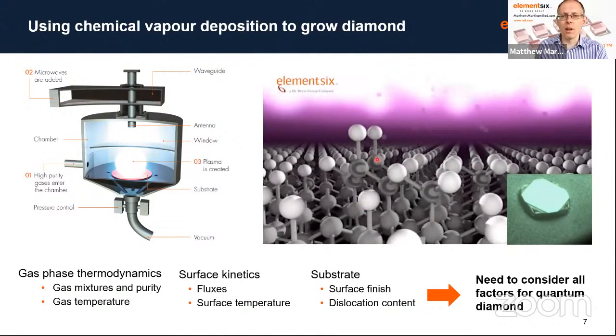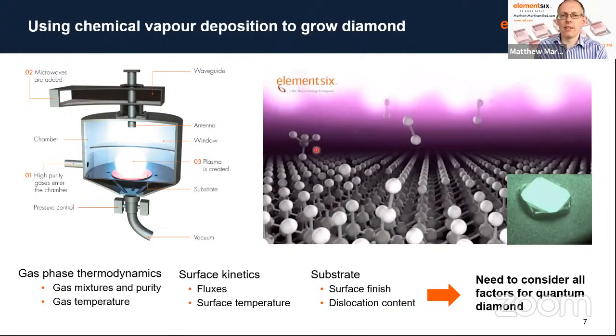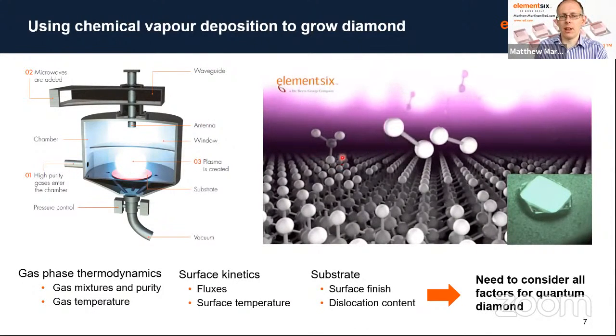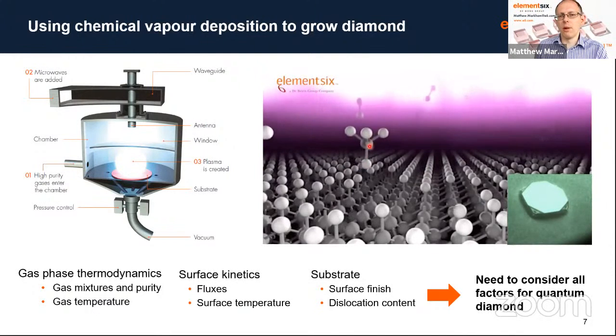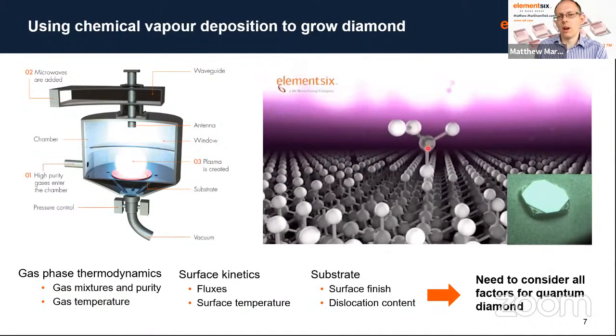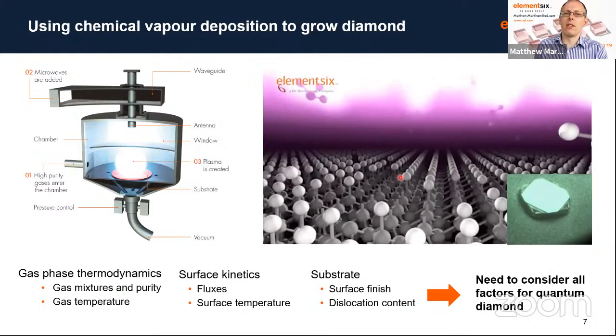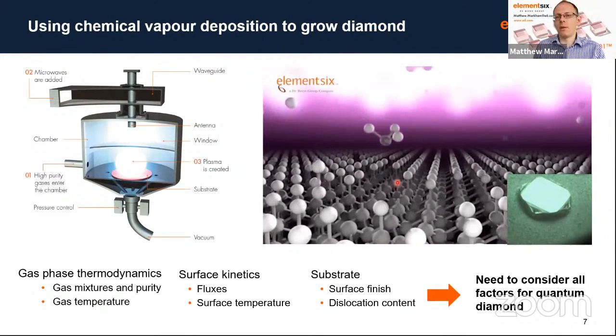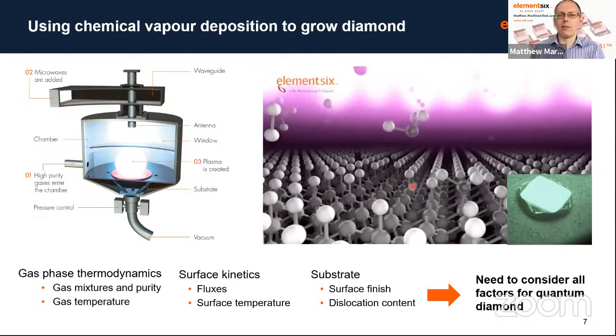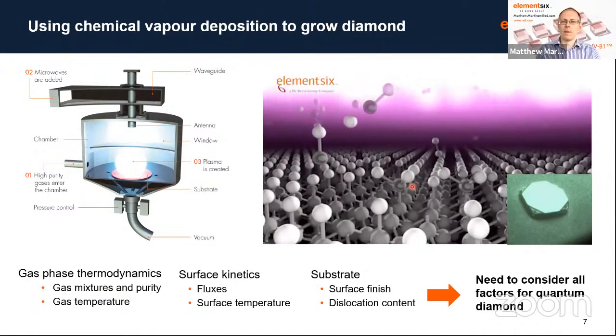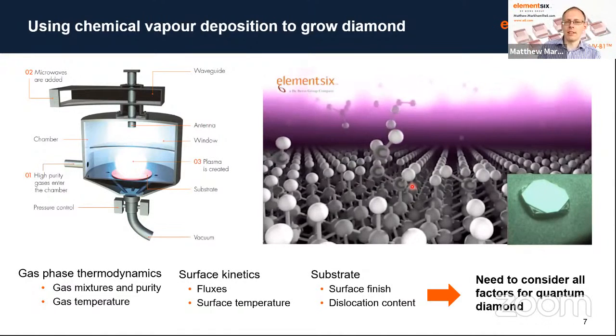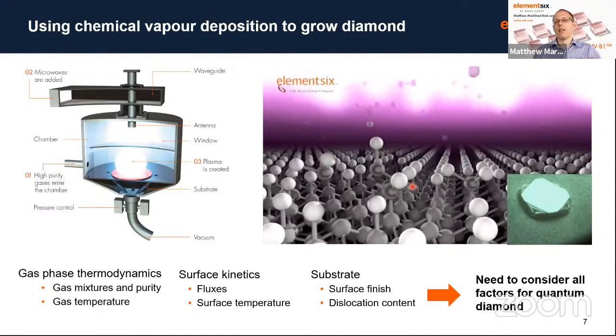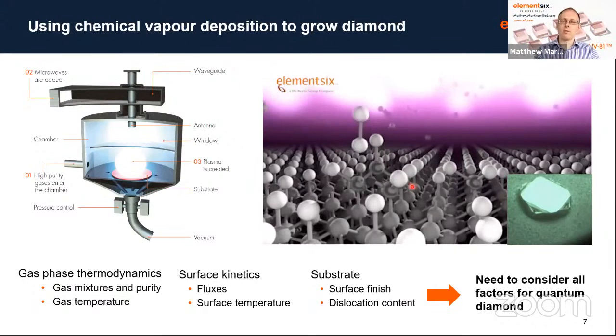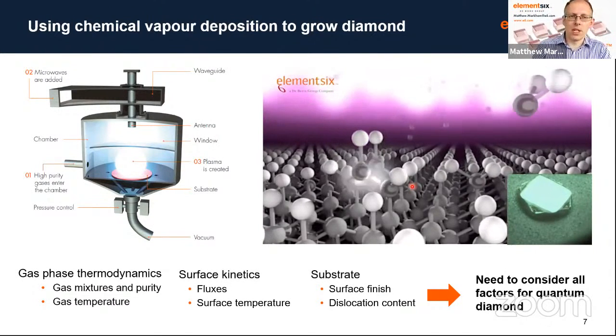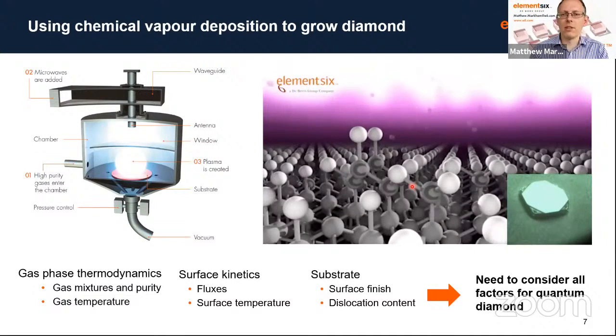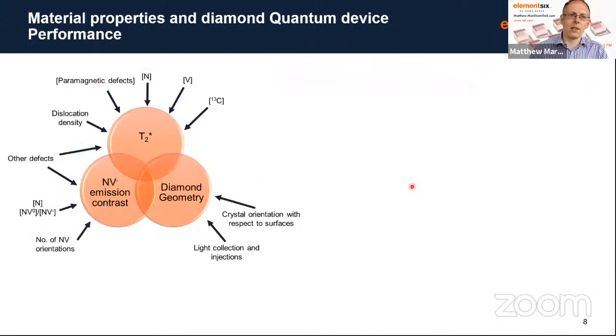So hydrogen really plays a key role in this, where firstly it creates the species. If we look at this methane here, we'll see a hydrogen come along and knock off one of the other hydrogens, creating a methyl radical, and it's those methyl radicals that then come in and build your diamond up. You've kind of got this bricklaying process, if you like, to build your diamond. And therefore you obviously can do it in layers. But there's a lot of factors we need to consider: the conditions, the temperature, the substrate, etc., when producing the material, because there's lots of parameters that go into the diamond which can affect the properties.